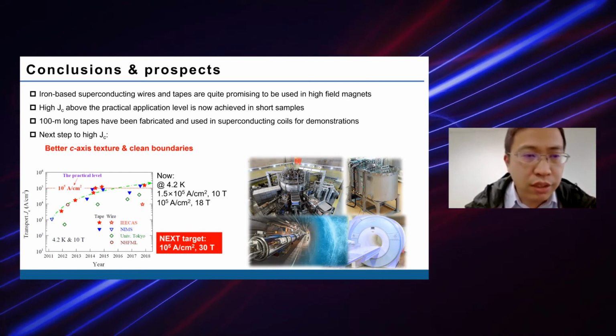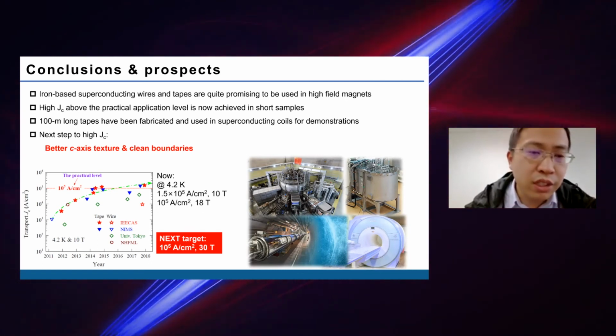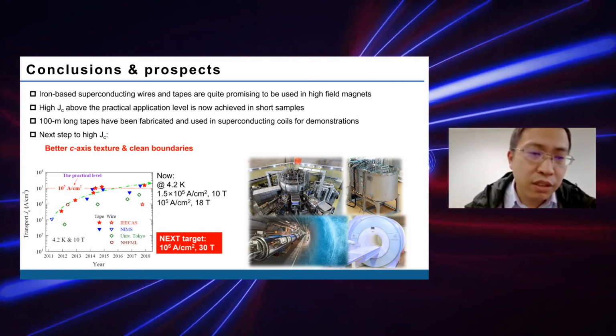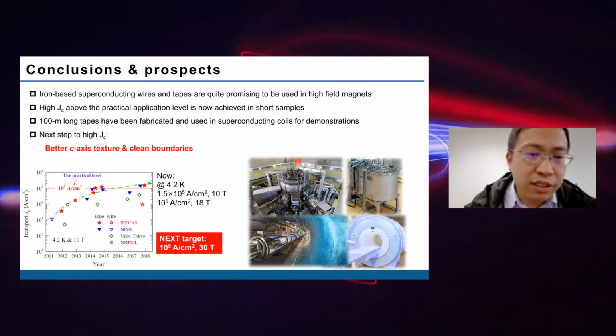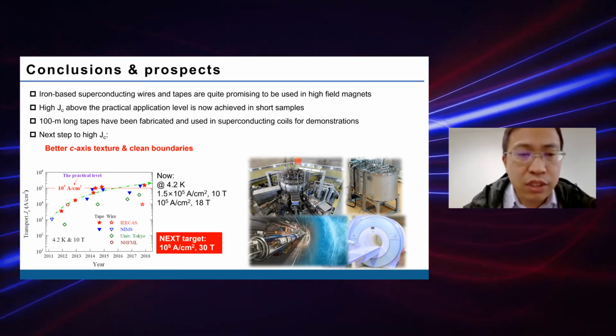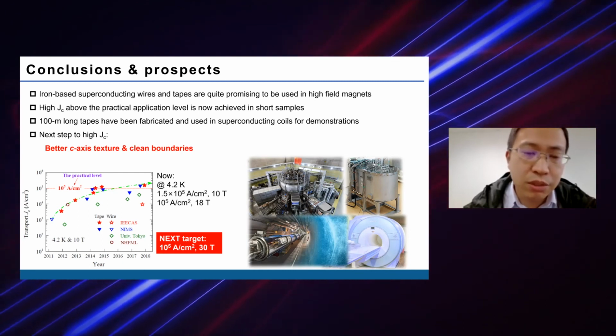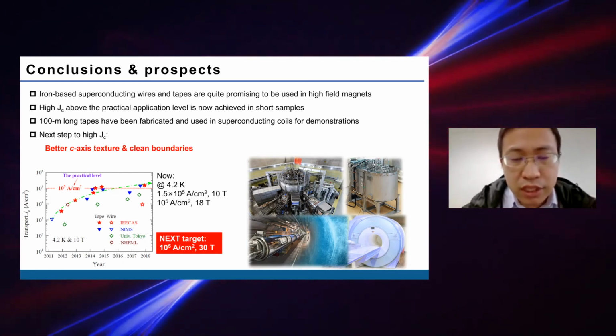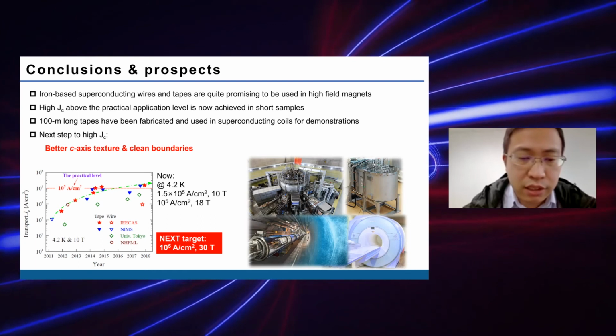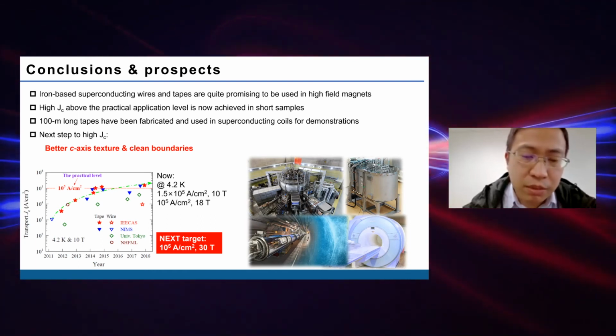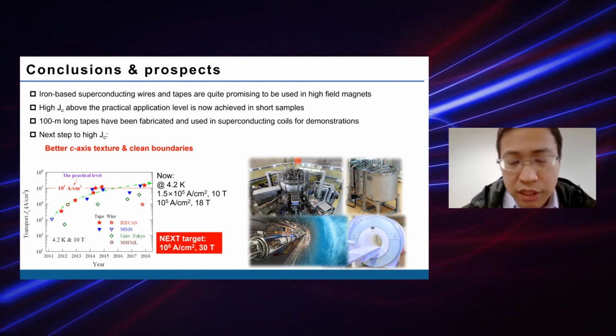And the next step to high Jc, in my opinion, we must maybe get a better c-axis texture and of course more clean grain boundaries. And our next target is 1,000,000 ampere per centimeter square at 30 Tesla.